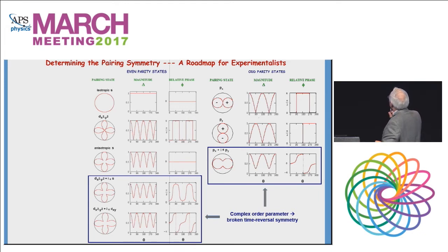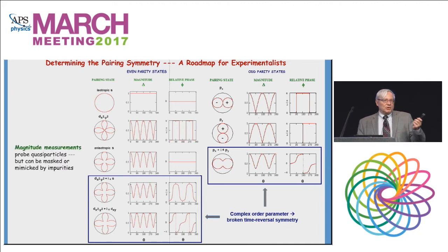What you do is you write down all the possible pairing states, including ones that are even symmetry, odd parity, even parity, odd parity, complex order parameters, and you write the magnitude and the relative phase as a function of k-space position. And if you do that, you can do experiments. So magnitude measurements, which most experiments are, essentially probe the number of quasi-particles. So they can determine where you are in these different pictures.